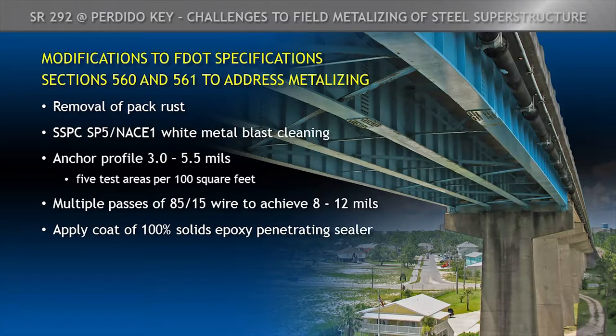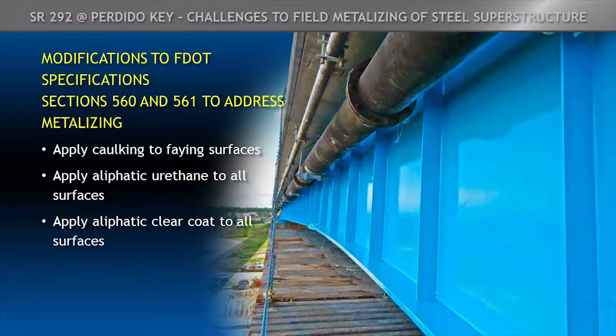And we required multiple passes of the wire, of the gun, to achieve 8 to 12 mils. We also applied a coat of 100% solids epoxy penetrating sealer to seal the porosity of the metalizing. Applied caulking to all the faying surfaces. You'll actually see a picture of the caulking here in a little bit. And then we top coated with aliphatic urethane for the blue color. And then we applied a clear coat to all the surfaces.